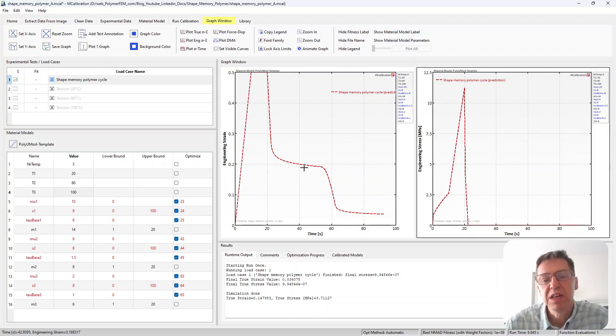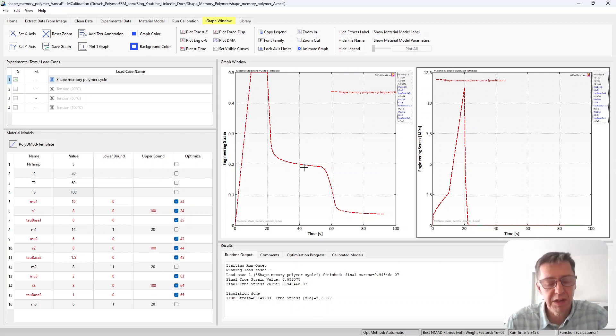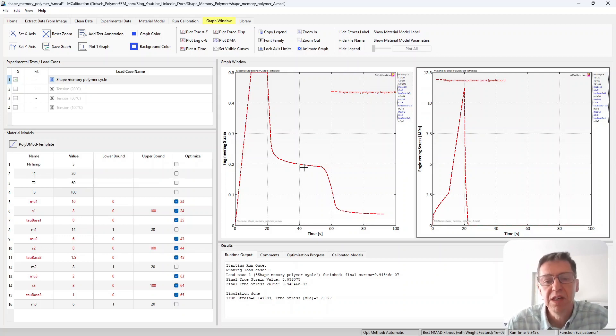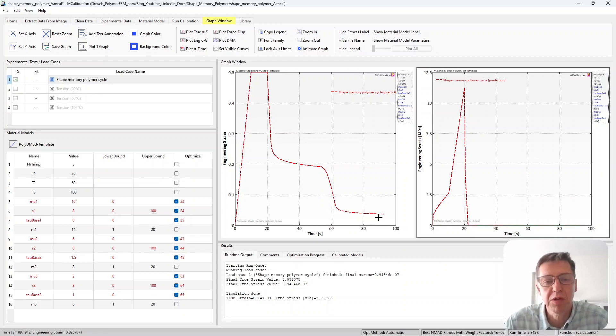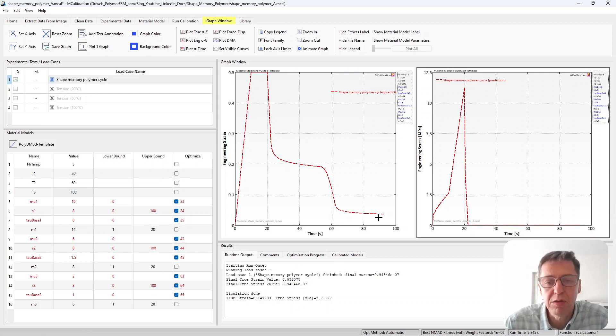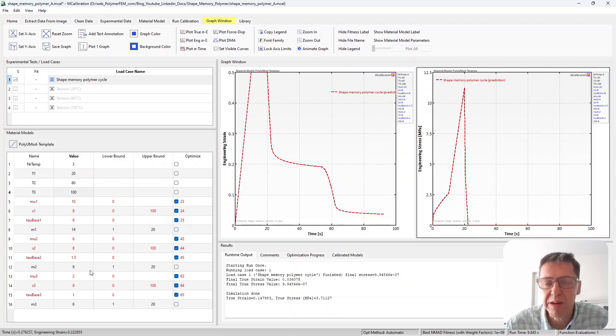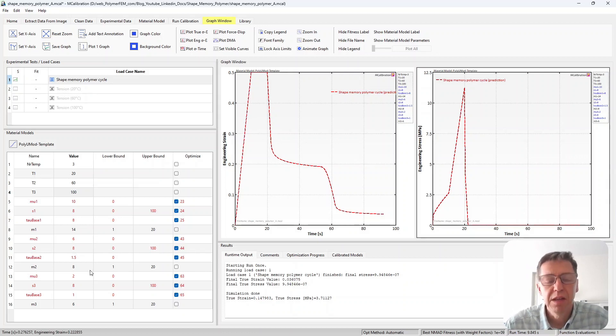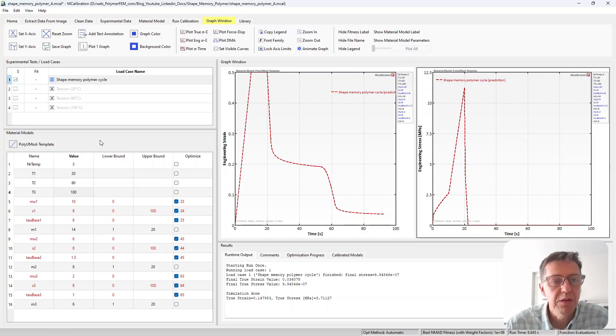And then we have about 20% residual strain at room temperature after that cycle. And then once we increase the temperature again, the material sits there, the specimen sits there, a lot of recovery occurs. It goes from about 20% strain down to about 5% strain. So it's a pretty substantial memory effect that occurs in this material during the final heat cycle. So this of course depends on the material model parameters and how much of this will recover during the cycle.